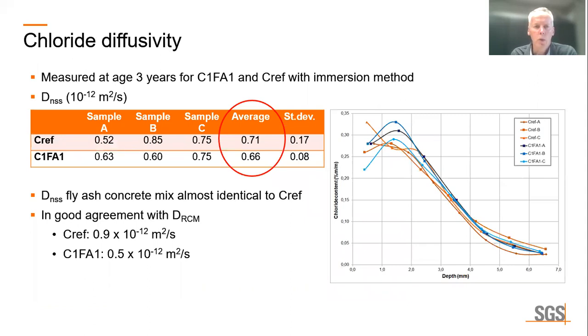Then we have the additional investigation, in which we have used the natural diffusion method to determine the chloride diffusivity for the reference concrete mix and 1 fly ash mix.